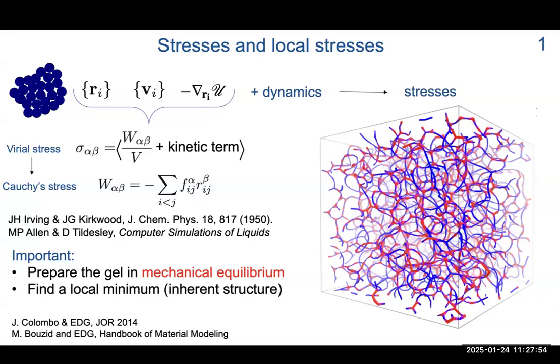So as the gel forms, depending on the kinetics of the self-assembly that we can tune by adjusting the interaction between the particles, so typically the temperature and the time over which the temperature has to change, so how fast do we let the system aggregate? This can produce different types of stress distribution in the network. And the type of stress distributions are related to the type of spatial organization of the network and this type of large-scale heterogeneities that I was talking about.